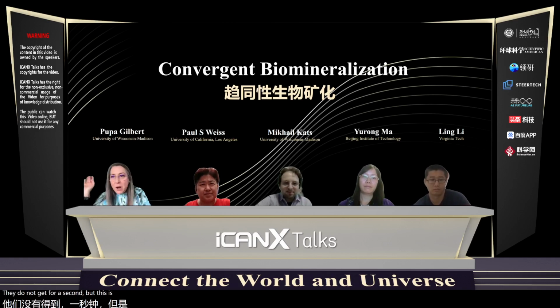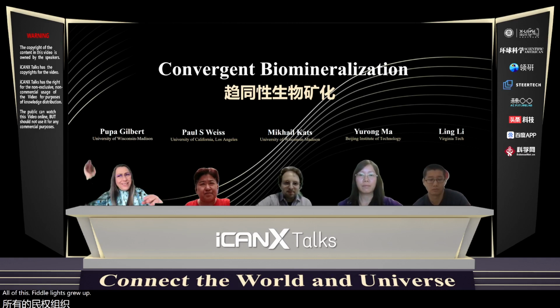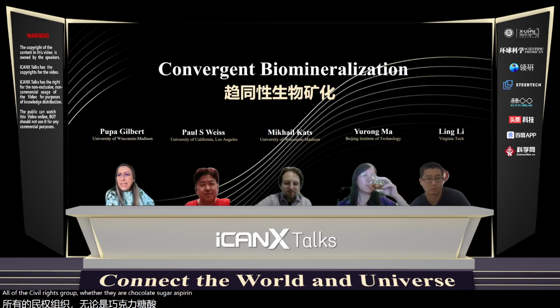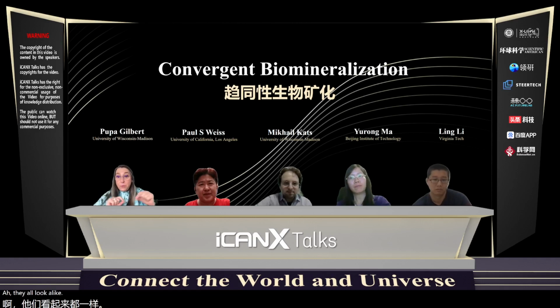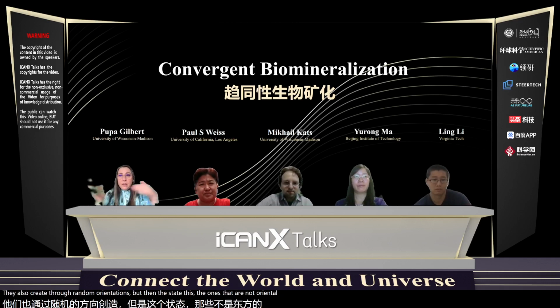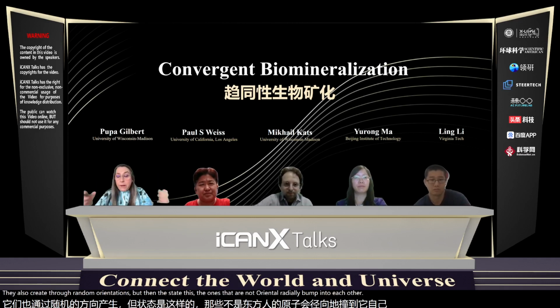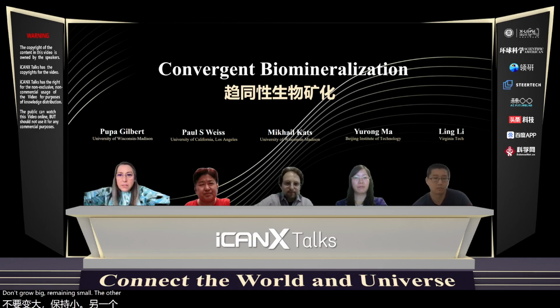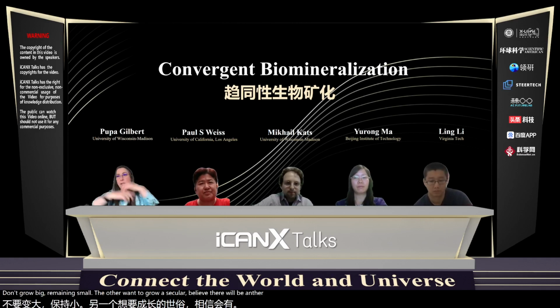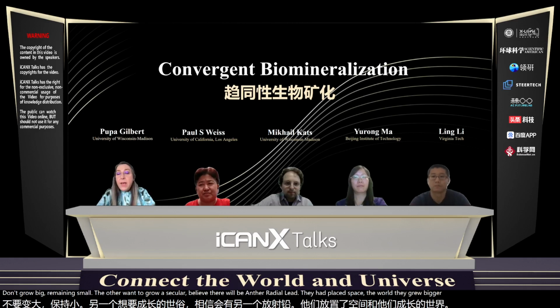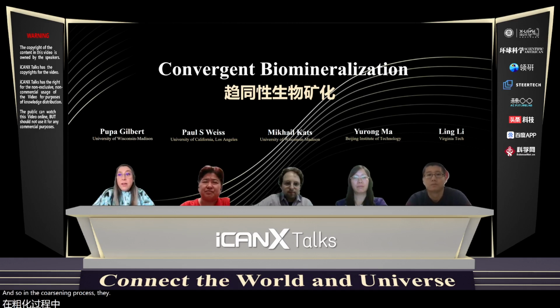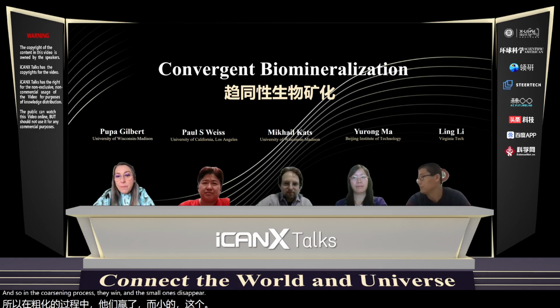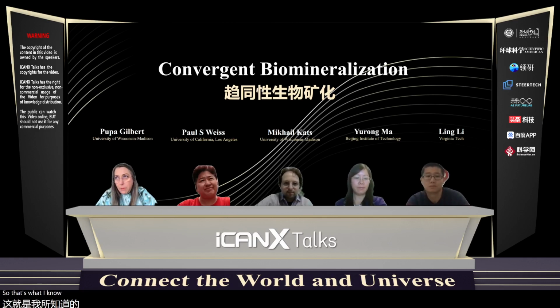But this is actually how all of the spherulites grow, whether they are chocolate, sugar, aspirin, or any other drug. They all nucleate with random orientations, but then the ones that are not oriented radially bump into each other, don't grow big, remain small. The other ones grow acicularly, they are oriented radially, they have space to grow, they grow bigger. And so in the coarsening process, they win, and the small ones disappear. So that's what I know about spherulitic growth. How it actually happens in coral skeleton is pretty clear.